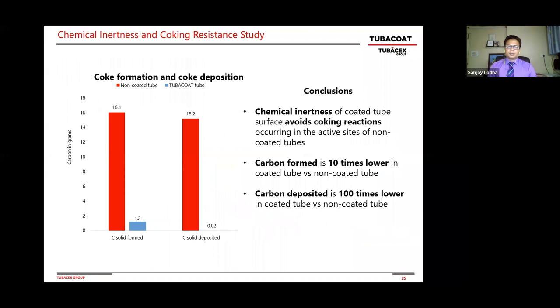So in summary, the chemical inertness of the coated surface avoids coking reactions. Carbon formed is 10 times lower. And whatever carbon is formed, the deposition of that carbon is 100 times lower. So significant improvement both in carbon formation and carbon deposition with these coated tubes. Next slide.